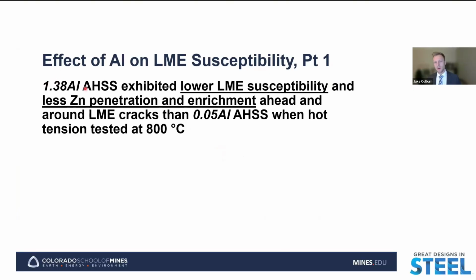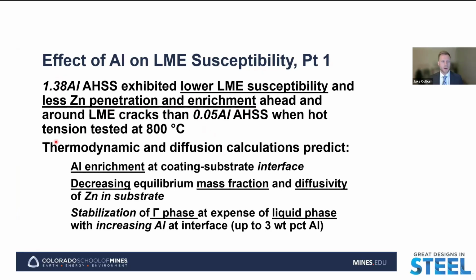see that the higher aluminum alloy showed lower LME susceptibility and zinc penetration and enrichment compared to our low aluminum alloy. And from those thermodynamic and diffusion calculations, we predicted potential aluminum enrichment at the interface, a decrease in the equilibrium mass fraction and diffusivity of zinc in the substrate, and then again, the stabilization of this beneficial gamma phase at the expense of a detrimental liquid phase with increasing aluminum at the interface, again, up to roughly 3 weight percent aluminum. And above that, the liquid phase begins to be stabilized to a greater degree again.